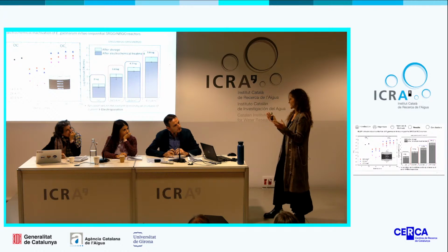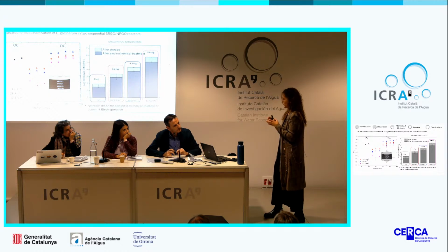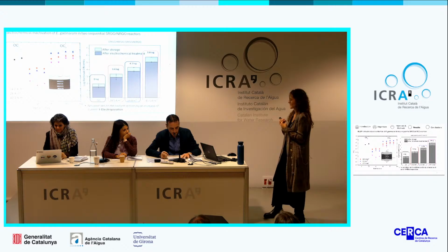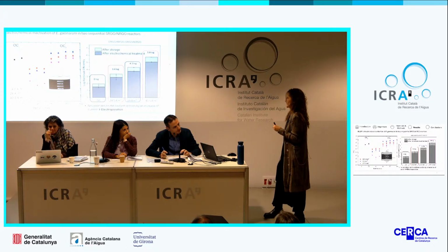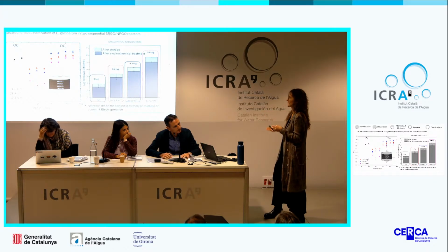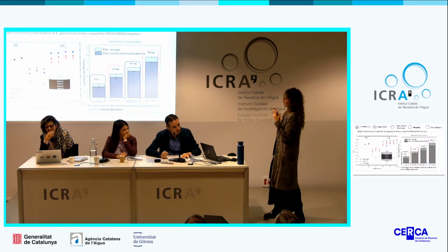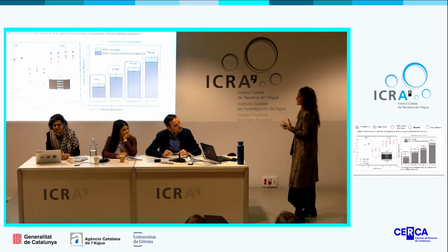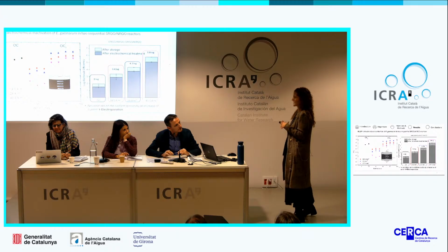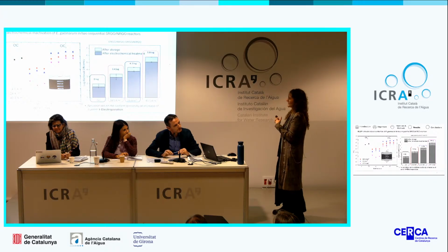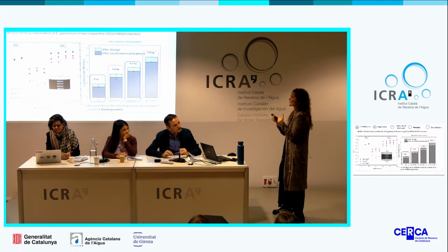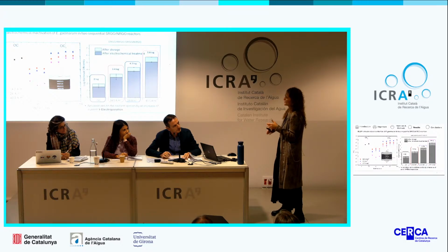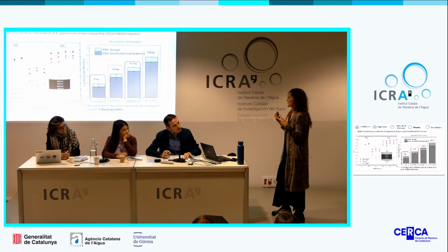So we were, as a first trial, working on that with this anode in our first study. But since in our first study we could observe that using drinking water as a background electrolyte, we didn't have enough interaction between the electrolyte and the surface of the anode, we decided to try with sulfur in order to enhance the hydrophilicity and wettability of the electrode.